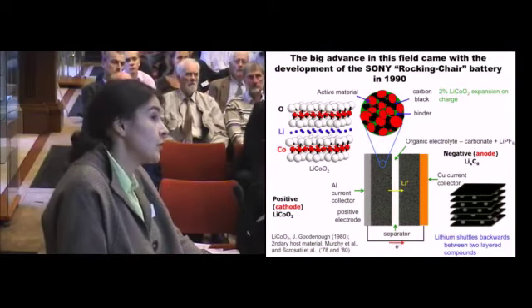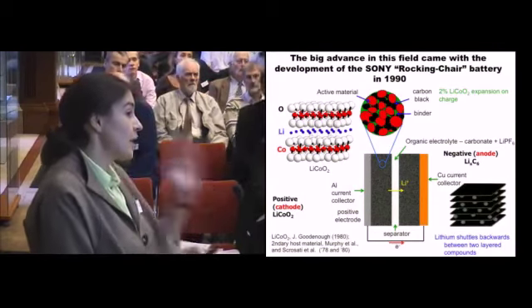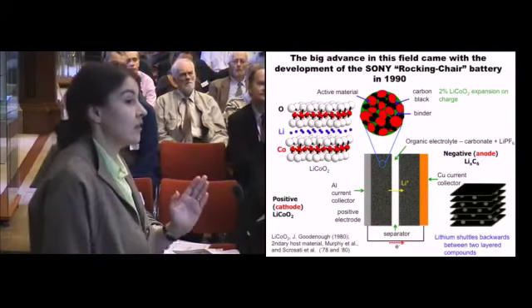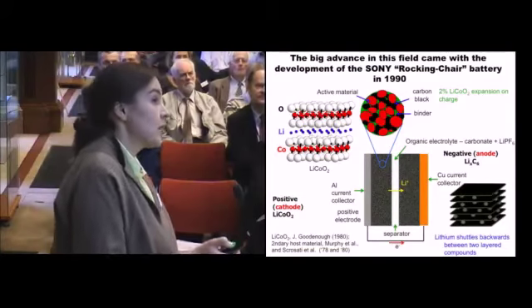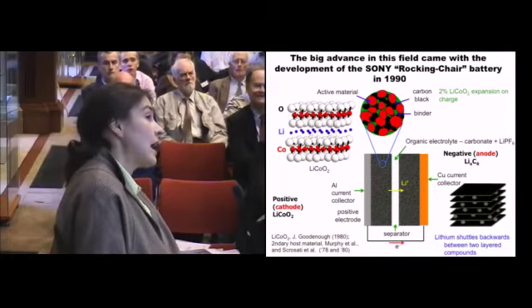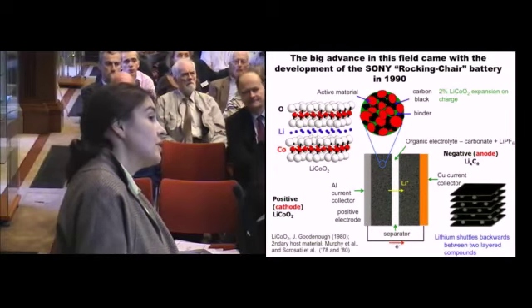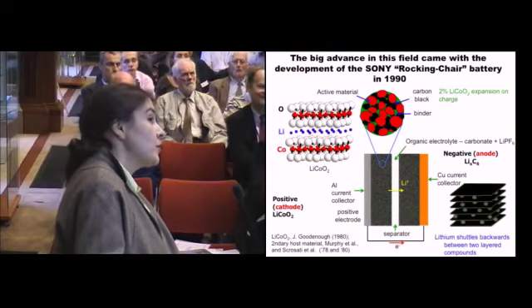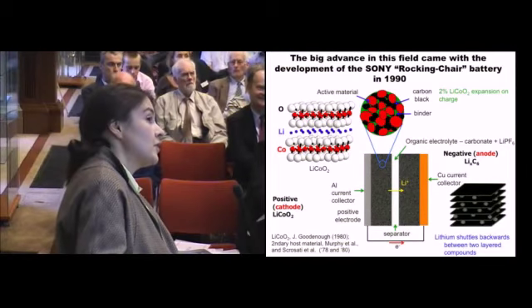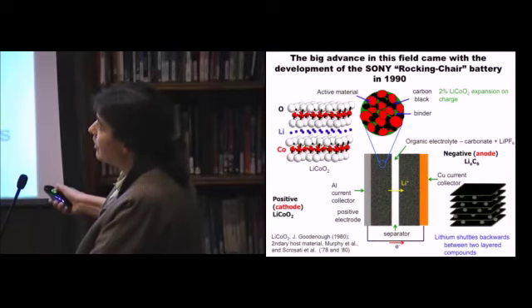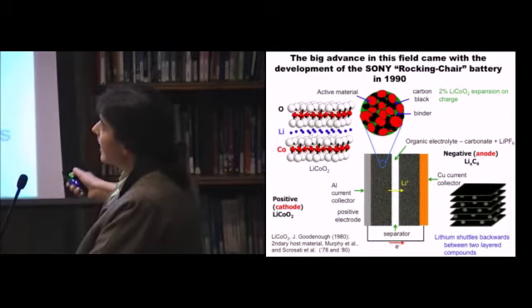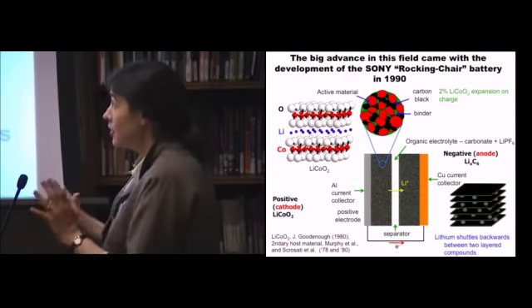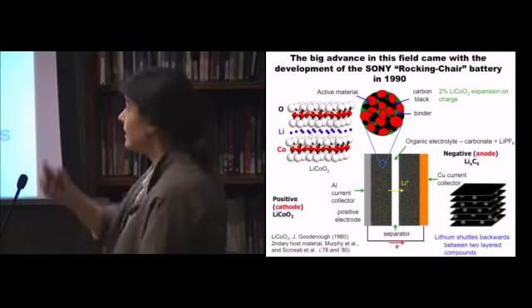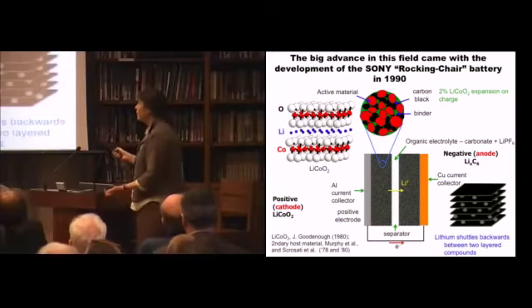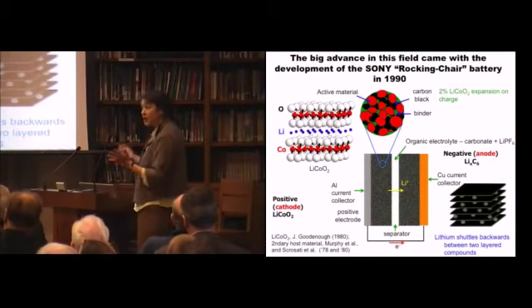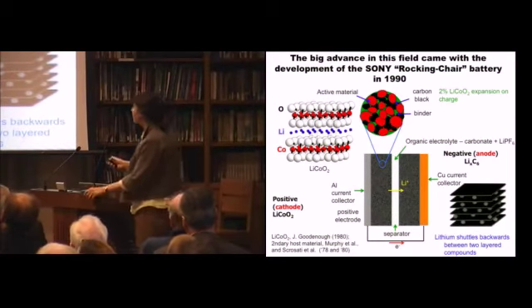So I just want to stress here that it's not just a simple system where you have a cathode on one side and the anode on the other side. You make these composite structures to get your battery to work. And so your composite comprises your active material, which is, in this case, the lithium cobalt oxide. You put extra particles of carbon to create a percolating network that's conducting. So you can get the electrons in from the current collector through the carbon to the particles that you want to access. And then you hold it all together with a plastic binder so that as you pull the lithiums out and the materials flex slightly, so there's about a 2% expansion of lithium cobalt oxide as you pull the lithiums out, you can hold it all together without losing contact between the particles.